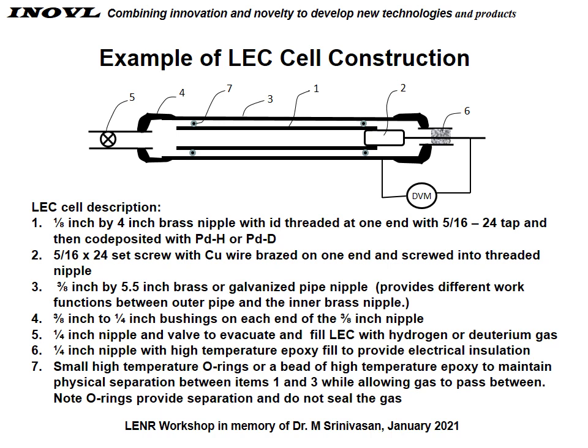At the other end, the nipple has a high temperature epoxy fill with the wire passing through to provide electrical insulation and also seal the inside of the LEC. Small high temperature O-rings or a bead of high temperature epoxy is used to maintain the separation distance between the working electrode and the counter electrode while allowing the gas to pass between.